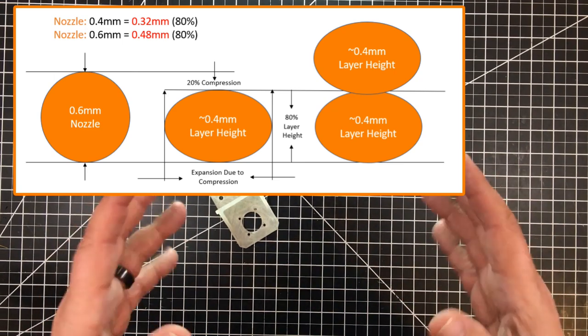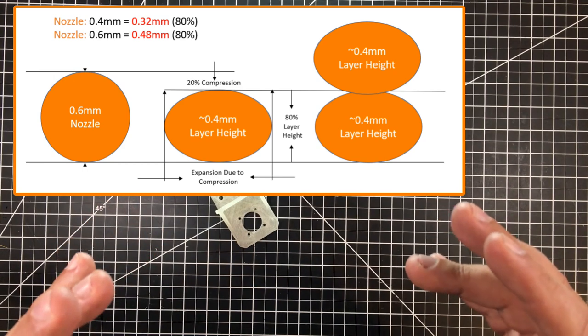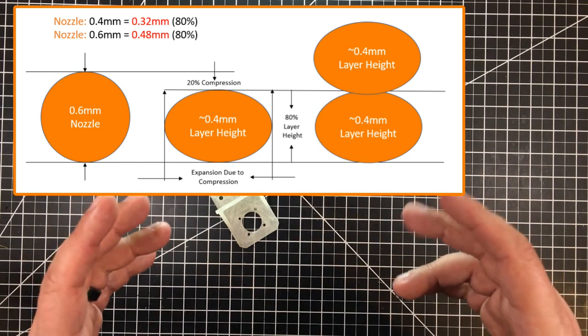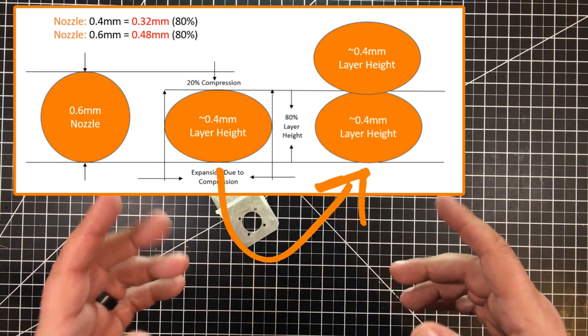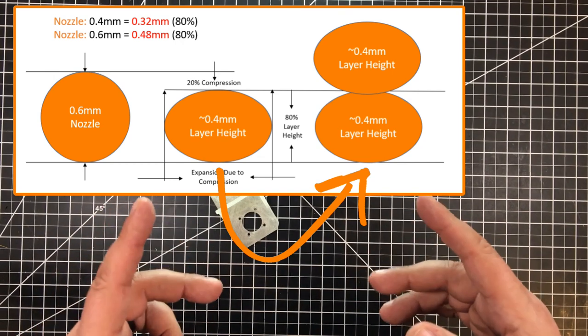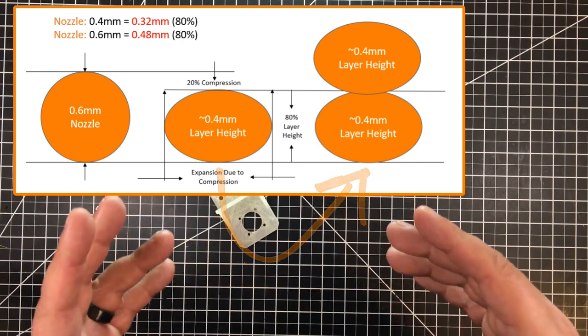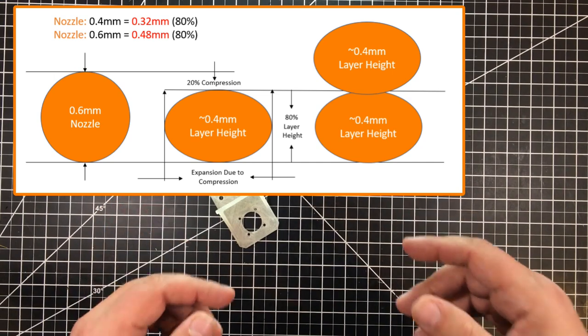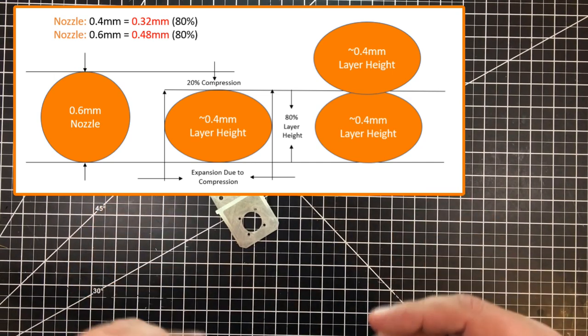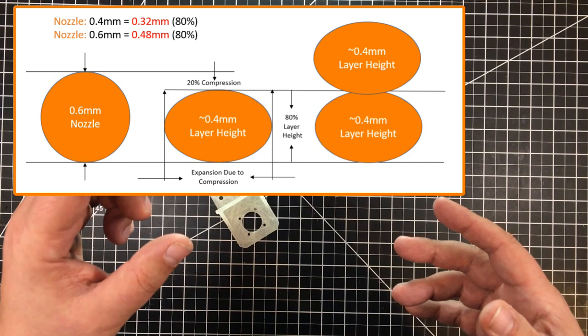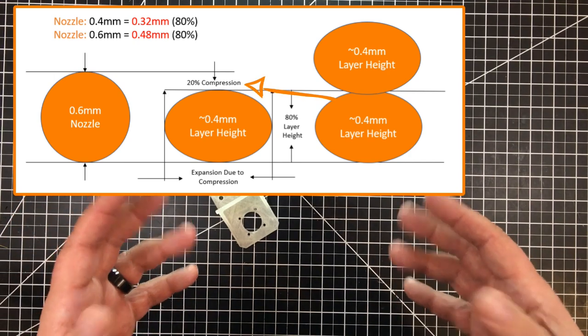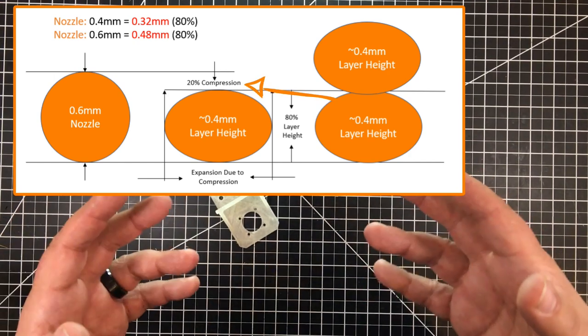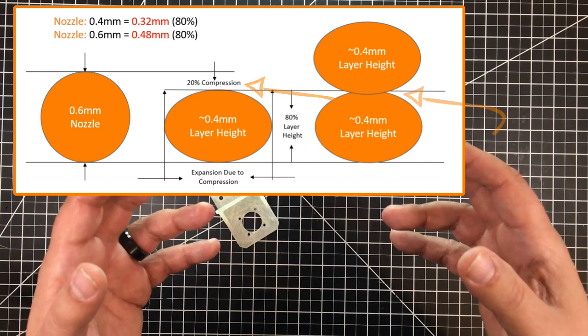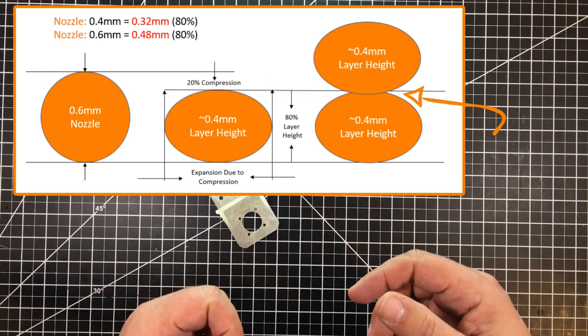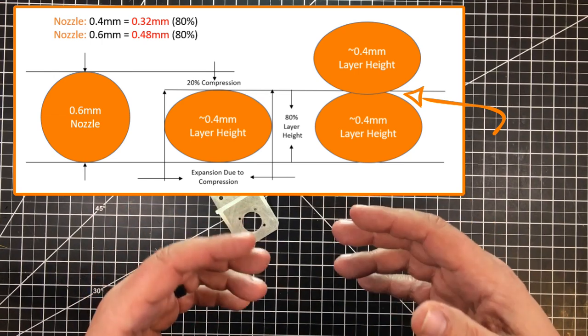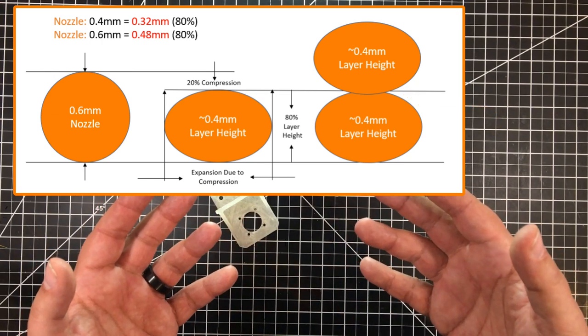The situation you have to keep in mind with this number is, again, you're not laying down a circle when you're putting down plastic. There is a compression factor where the nozzle is actually pushing down on the plastic and creating an oblong. So with this 80% rule, 20% of that is ending up as compression. You need to have that compression to get a robust print, where it's going to push those two layers together. If you don't do that, then you run the risk of delamination.